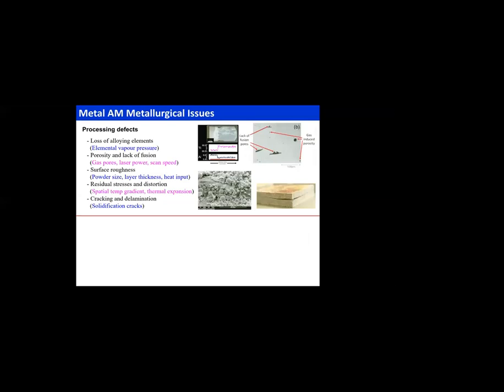Now I come to a brief on AM metallurgical issues. What are the processing defects you can see? There can be loss of elements. All the elements which have a low melting point may evaporate from the bed, and finally your composition may not be what you want. There may also be porosity or lack of fusion. There may be some gas entrapment in the material during melting, or, as I showed you earlier, some powders may not be fused altogether, or may not be properly sintered. If they are not fused, they will be separate and will be seen in the microstructure in the form of pores.